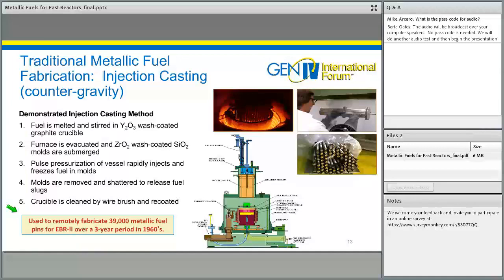I said previously that this is a process that is very amenable to deployment in a remote or hot cell environment. In fact, that's not just a theoretical statement. This was in fact done back in the late 1960s at EBR-II. Over 39,000 metallic fuel pins were fabricated in the hot cell, introduced back into EBR-II to demonstrate their performance over a 3-year period. And there were no issues associated with that.